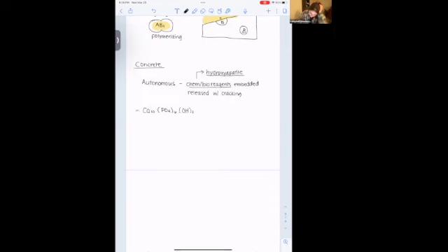And this generalized form here is the stoichiometric form. Bone is actually non-stoichiometric. And so it doesn't look exactly like that formula. You can get CDHA, which is calcium deficient hydroxyapatite. So that just means that you have a reduced calcium to phosphate ratio. And then you can also get CCDHA, which is carbonated calcium deficient hydroxyapatite. So again, we're decreasing that ratio, but we're also replacing certain groups with carbonate.